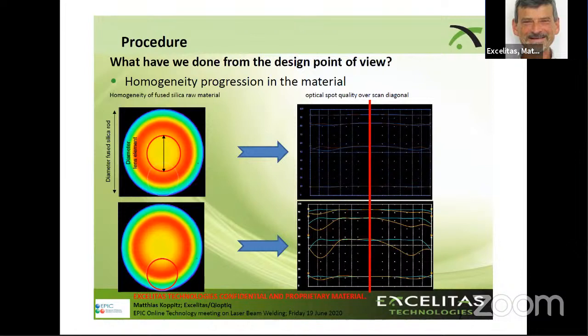On the right side, you see the spot quality over the scan diagonal, or over the image field. The red line is the optical axis, so on axis, and you see a more or less very constant optical spot quality. When we go down to the red circle, the raw material for a lens element cut close to the edge of the rod, you see the spot quality on the right-hand side is not very constant over the scan field or image field. You have big variation, and this ends up in a quality variation of the spot. Next.